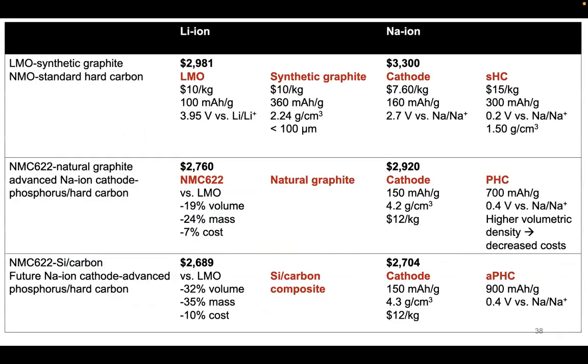Okay, so in terms of breaking down how these comparisons are made and where the costs are derived from, there's always a trade-off. So when you go from synthetic graphite to hard carbon, the trade-off there is the capacity decreases a little bit, down to 300 milliamp hour per gram versus synthetic graphite, which is 360 milliamp hour per gram. And in terms of reduction in costs of the cathode, you see currently the cathode would cost less, a sodium manganese oxide, say, at $7.60 per kilogram. And that's over the current price for lithium-ion battery cathode, lithium manganese oxide to be specific, at $10 per kilogram.